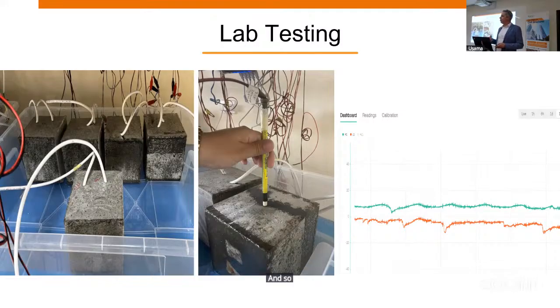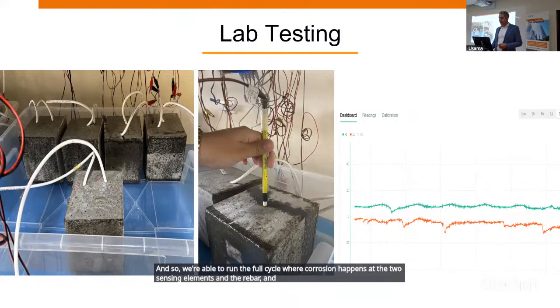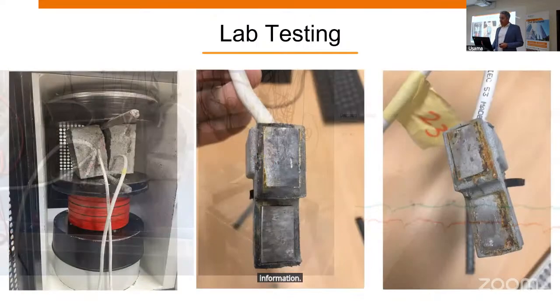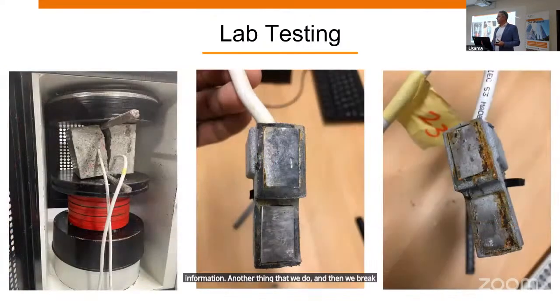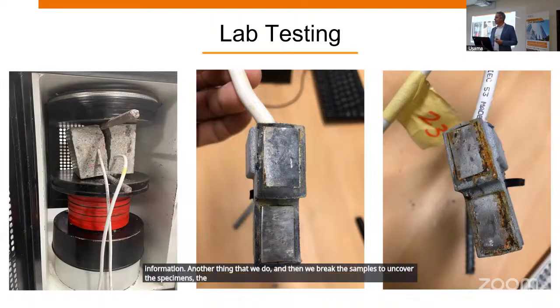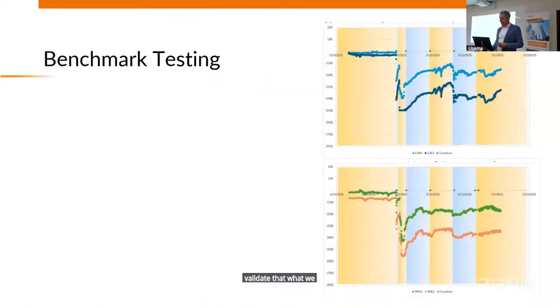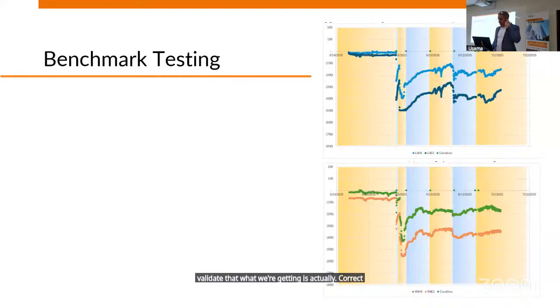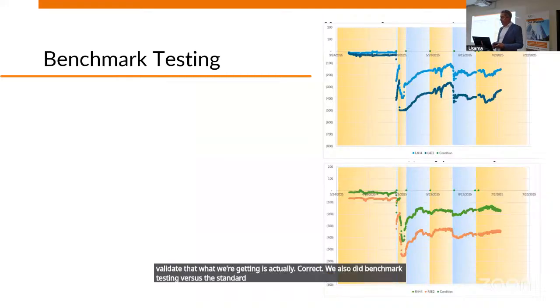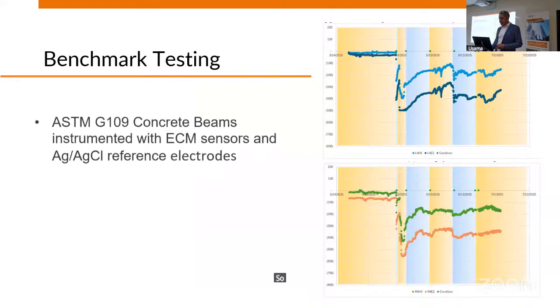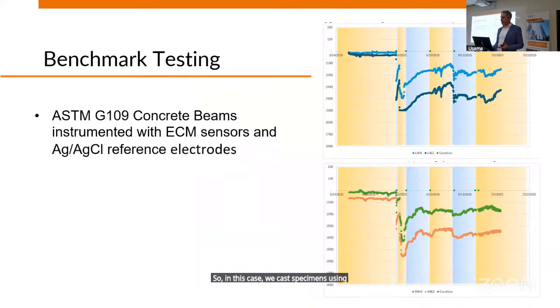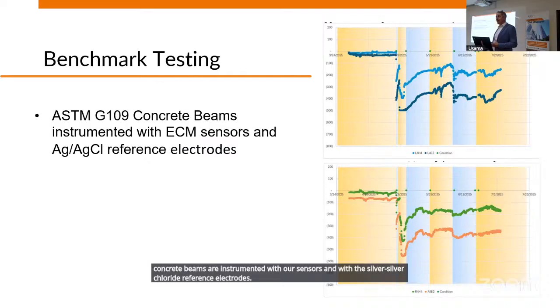And so we're able to run the full cycle where corrosion happens at the two sensing elements and the rebar, and we're still getting information. Another thing that we do is break the samples to uncover the sensors and validate that what we're getting is actually correct. We also did benchmark testing versus the standardized reference electrodes. So in this case, we cast specimens using the ASTM G109 methodology, concrete beams instrumented with our sensors and with the silver-silver chloride reference electrodes, and data was collected over time.